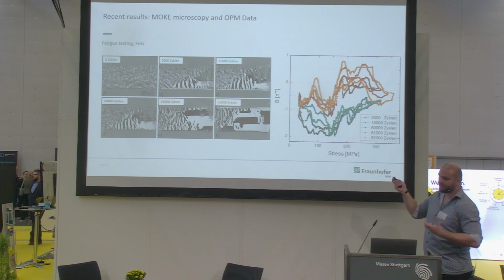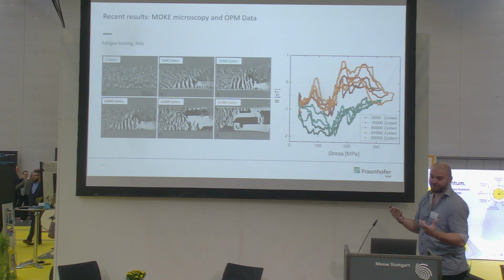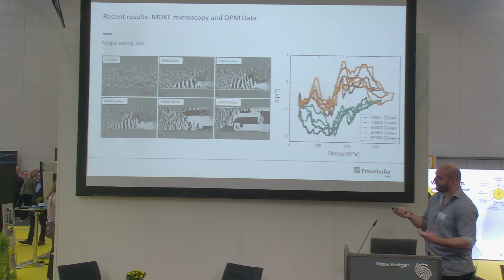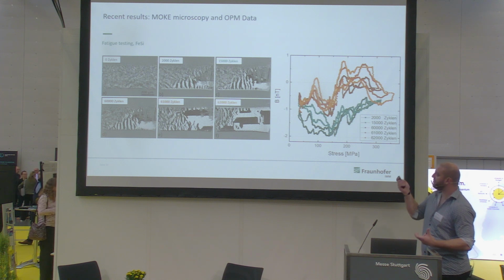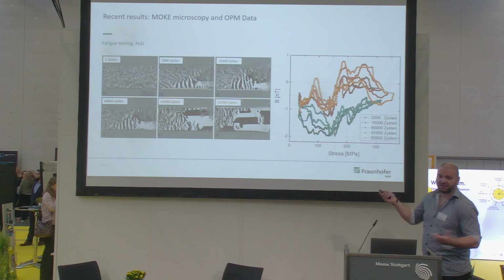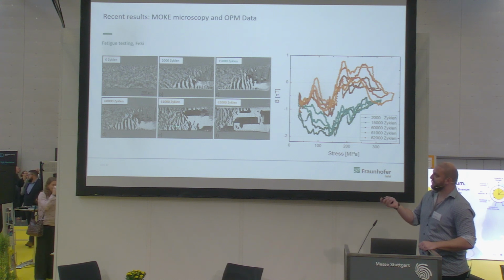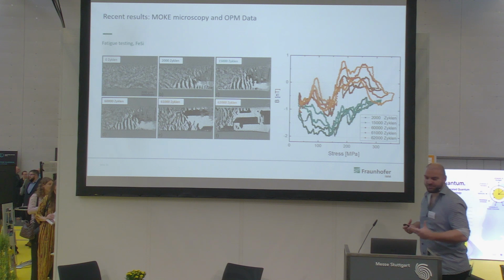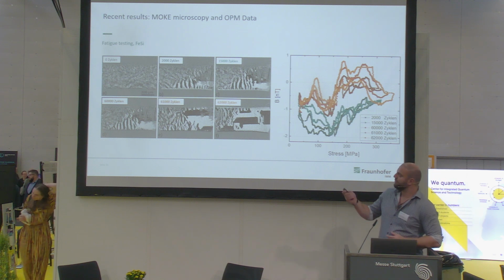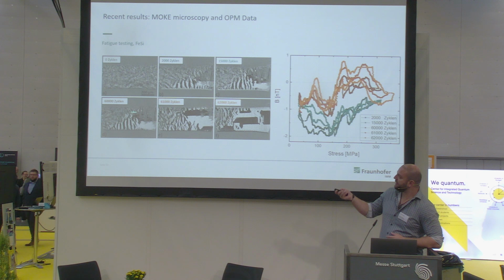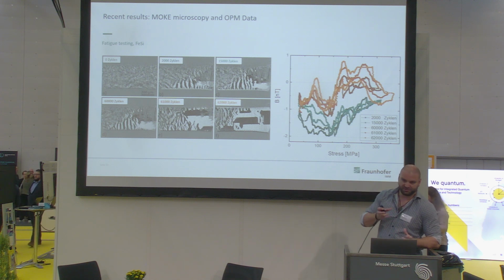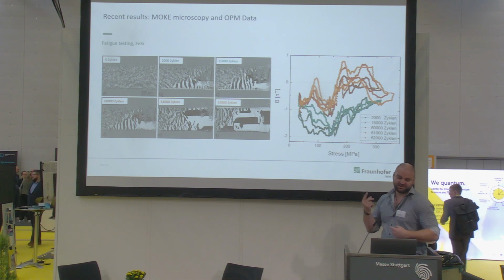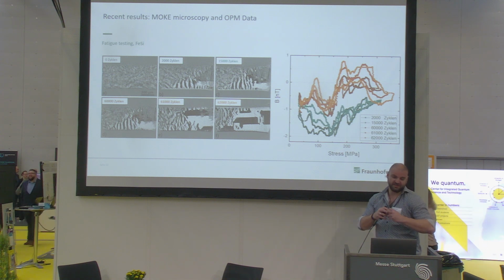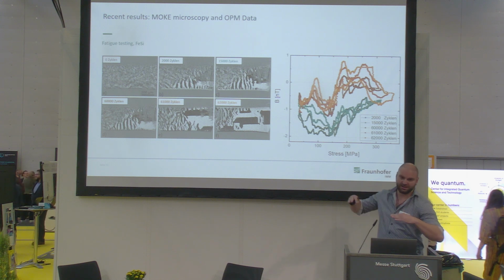So the magnetic signal, which is generated by the whole sample, the inside part of the sample, moves up and stays at a certain level. And this is already happening where we don't see anything yet in MOKE. Only at the end, this pattern on the surface is evolving. So the hypothesis that we have now is that between here and here, most of the magnetic state is already fixed to some sort of damage. This means that the magnetization is fixed in the center of the sample first, and the surface is only aligning in the end.